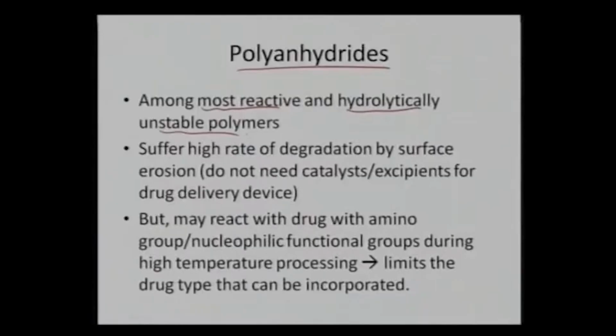First of all, the advantage is that they suffer a very high rate of degradation because of the surface erosion. So they do not need any external catalyst or excipients for the release of the drug. So in one case, we can induce a very high rate of drug release without any external catalyst or excipients, and still they will suffer a very high rate of degradation, just by engineering the combination of aliphatic or aromatic polyanhydrides. But at the same time, because of their high reactivity, they can also start reacting with the drug itself, which is being released into the body.